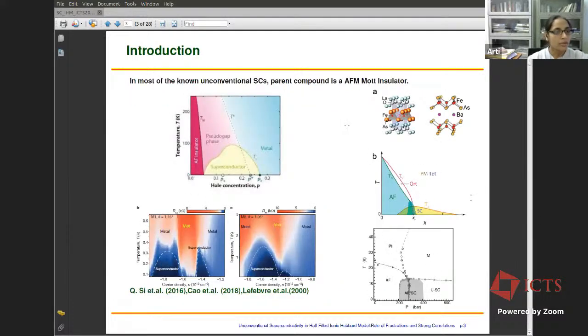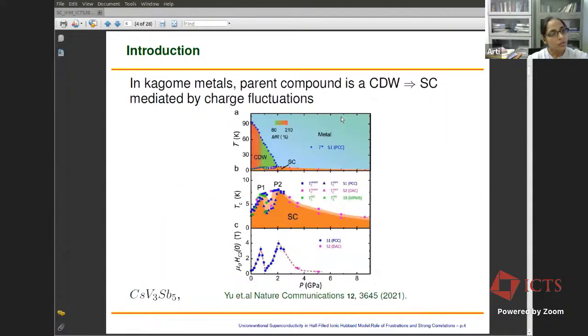So in the previous materials which I showed, since the parent compound is an antiferromagnetic Mott insulator, the common understanding in the community is that the superconductivity appears because of the spin exchange interaction, which basically provides a glue for Cooper pairing. But in these type of materials, where the parent compound is a charge density wave insulator, of course the pairing is not coming from some kind of spin fluctuation, but it must be provided by some kind of charge fluctuations.